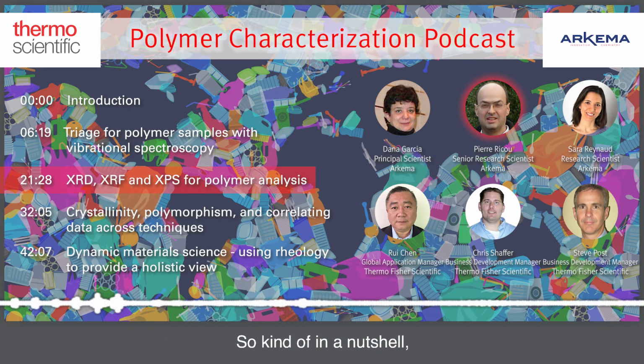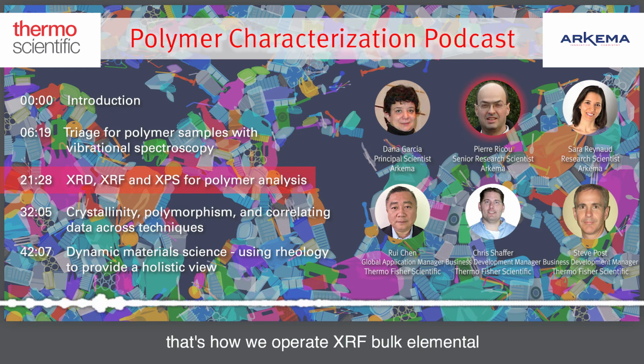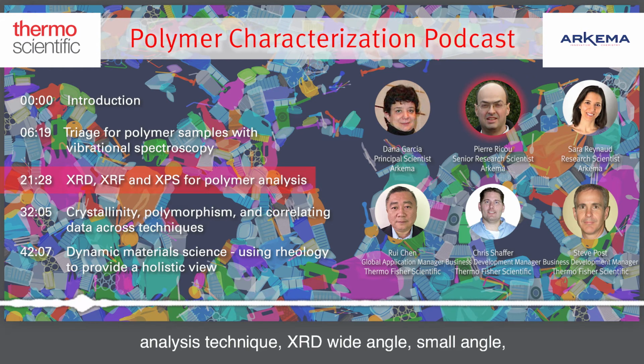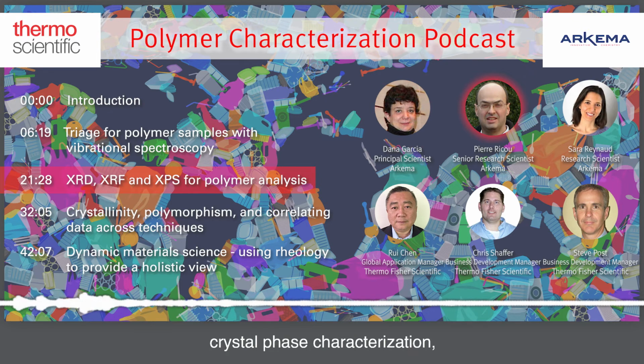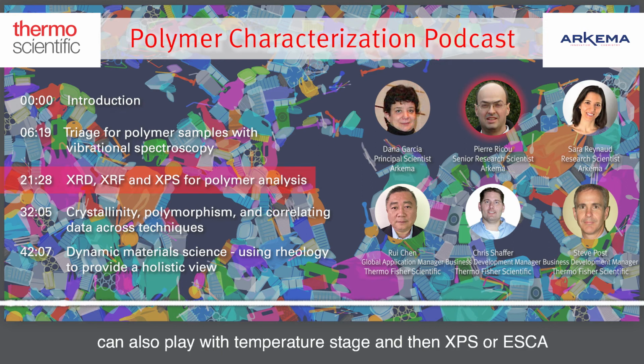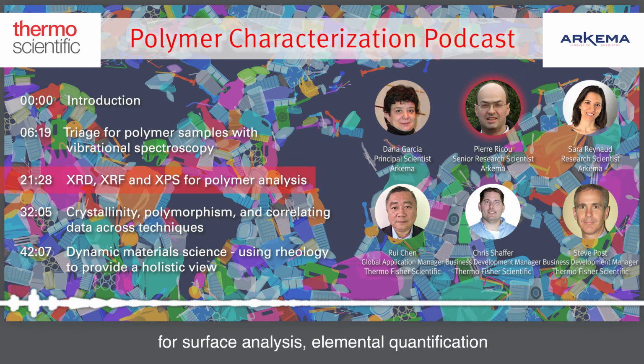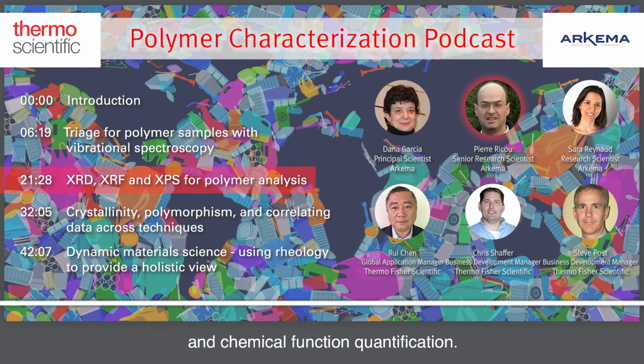So in a nutshell, that's how we operate: XRF, a bulk elemental analysis technique; XRD, wide angle and small angle, for crystal phase characterization, crystallinity, crystallite size, orientation, and other aspects where you can also play with a temperature stage; and then XPS or ESCA for surface analysis, elemental quantification, and chemical function quantification.